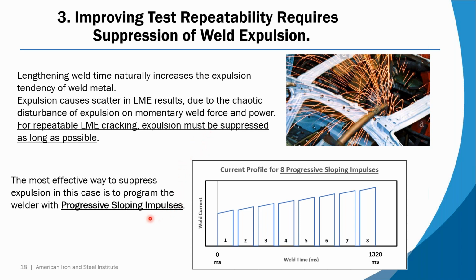So what we found is an effective way to suppress the expulsion is to use progressive sloping impulses. We have a whole bunch of pulses here. We're starting at a low current, and within each pulse we're using upslope, but it's progressive because pulse 2 begins where pulse 1 left off in terms of current. So it's gradually going higher, higher, higher. That technique allowed us to delay the time when expulsion occurs, so we have all of this crack development time down in the beginning of the weld schedule.